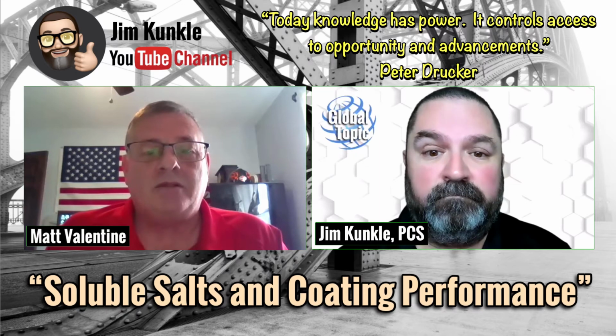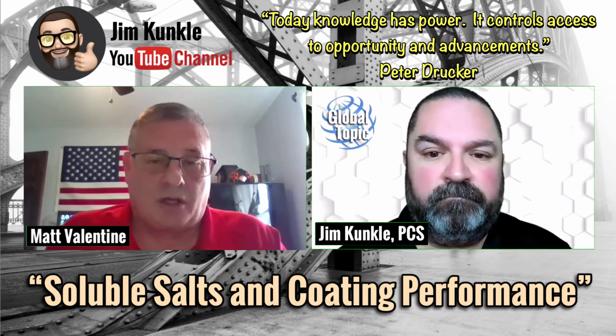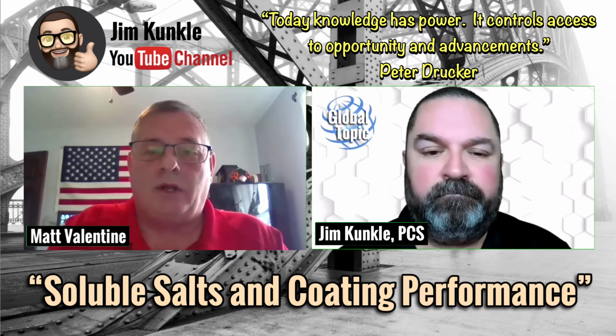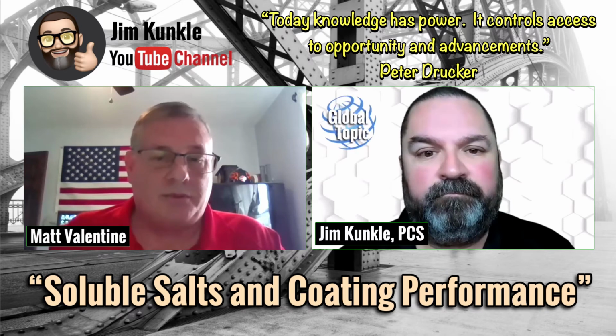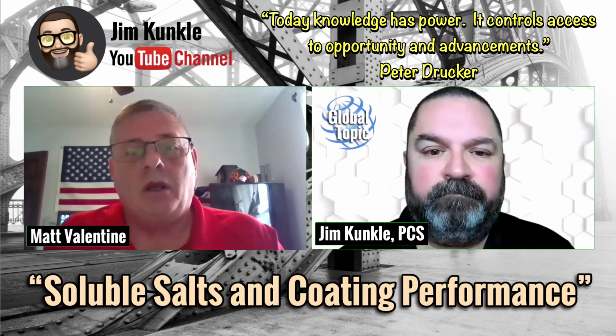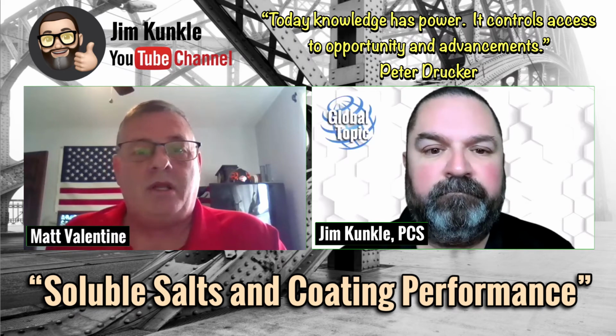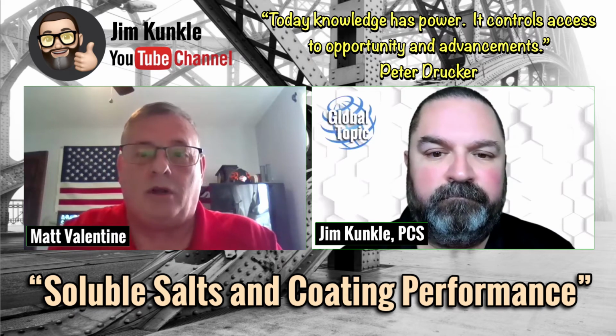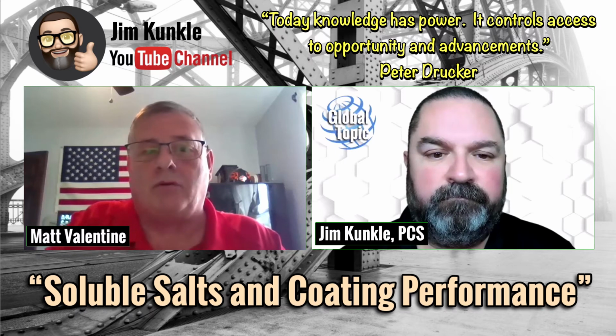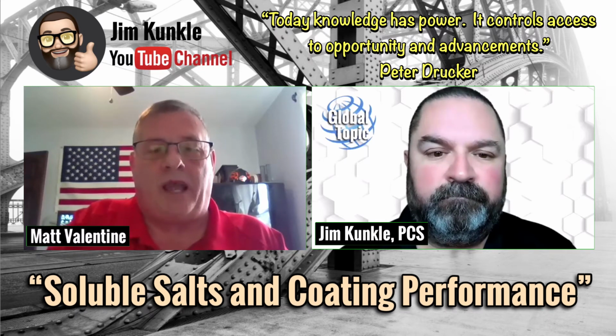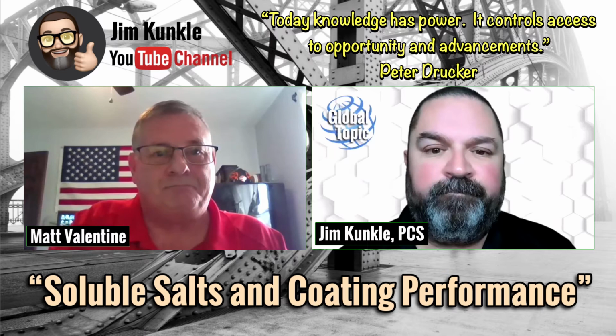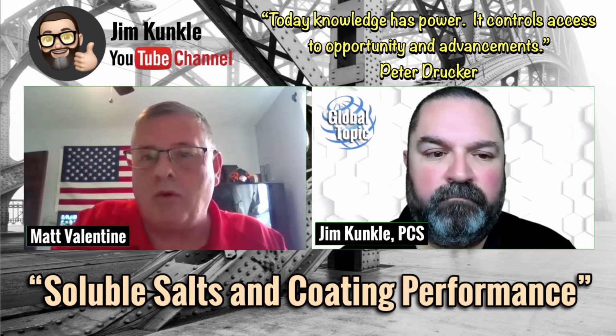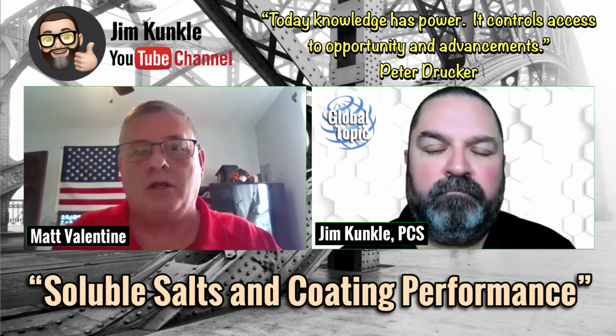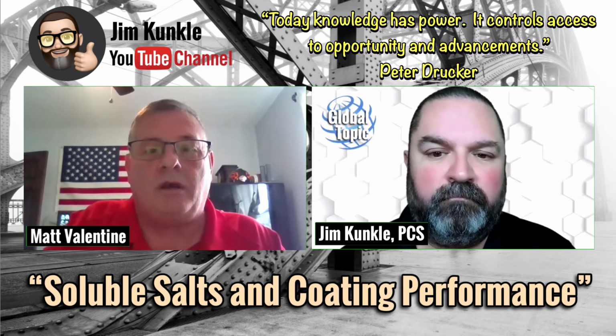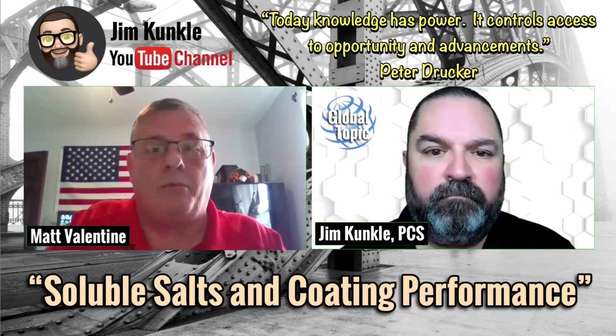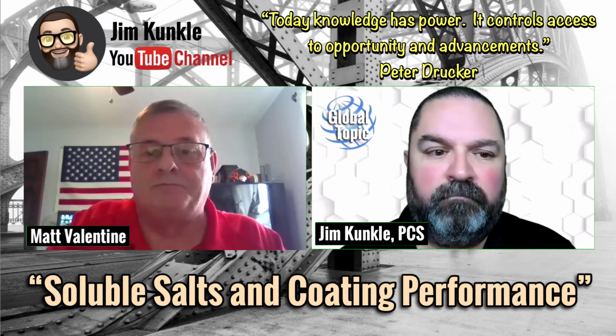And that's what creates the corrosion cell. It's not like you're seeing droplets of water passing through. It is the moisture vapor in the air that will actually permeate that coating, and it will create a corrosion cell. It starts out looking like a pinhole, and then it'll start undercoating and corroding up underneath the coating system. And eventually the coating system will fail.